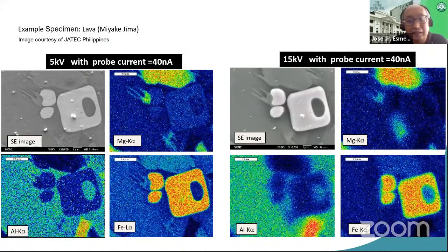This is illustrated in this next image. In a sample like this, at 5 kilovolts with a probe current of 40 nanoamps, you can see the details of the mapping. But when you increase the acceleration voltage further to 15 kV, you can see that the spatial resolution is now affected. So you won't get a good resolution of the images. That's why it's very important also to know the density of your sample.